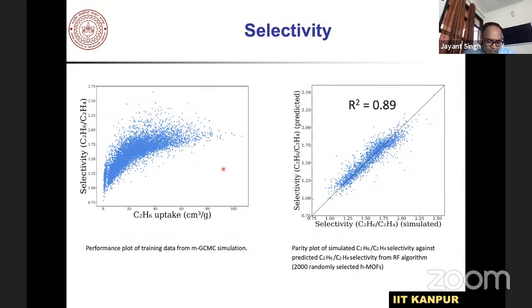I'll just show you a bit of the results. This is the selectivity of ethane with respect to ethylene, and this is the ethane uptake. Essentially, what we are looking for is high selectivity of ethane, because we would like to adsorb ethane out of the ethylene mixture, and the amount of adsorption should also be very high. So we can see that, for example, this one would be very good for us. Anything in this range is good. These data points, that means thousands of materials we have done simulation on,